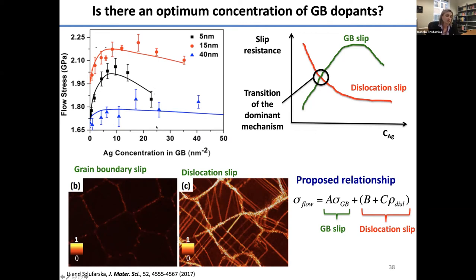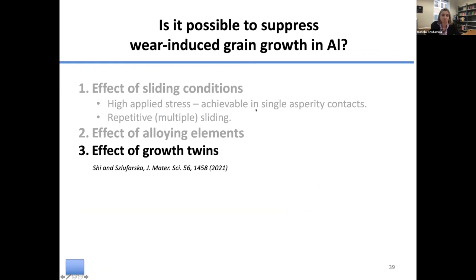Why is that? It turns out there's a change in deformation mechanisms for lower and higher concentration of dopants. Below, I show a picture of the von Mises strain. The brighter color tells us where the deformation is localized. For a small concentration of dopants, we can see that there's primarily grain boundary sliding. When you increase the concentration, grain boundary sliding becomes more difficult and dislocation activity takes over. So we developed an analytical model that describes this transition, and in fact the model for the case of copper works very well. The lines in this image are from our model, and the points are from molecular dynamics simulations, with two fitting parameters. That means we can use these dopants to optimize the microstructure evolution, as well as the strength.